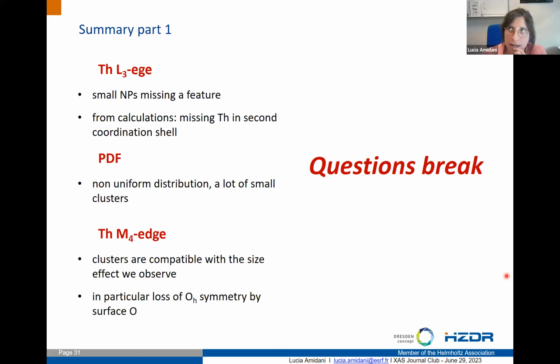Maybe I would conclude the contrary, in the sense that, as I said, I was totally not considering the white line. In the end, I showed a big variation in the surface atoms, which somehow remains unmeasurable. I didn't measure the surface atoms themselves, so I cannot say if the effect that I see in the white line resembles reality, because if we then do the weighted average of everything, the dramatic effect that you saw would be diluted in the core atoms. I didn't show the average, but let's say it is not so dramatic. Still, there is an effect that is not completely the one that we see in the data.